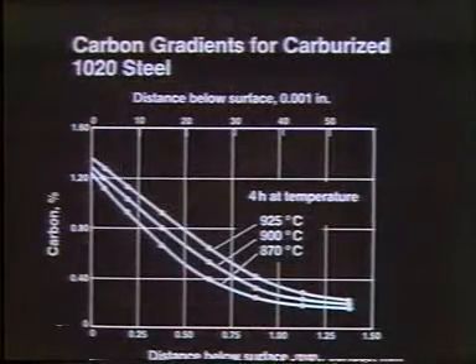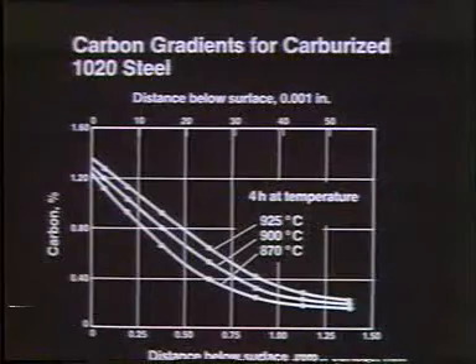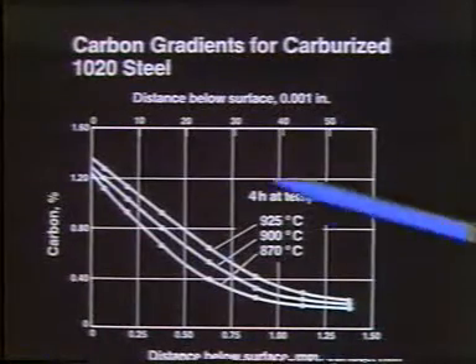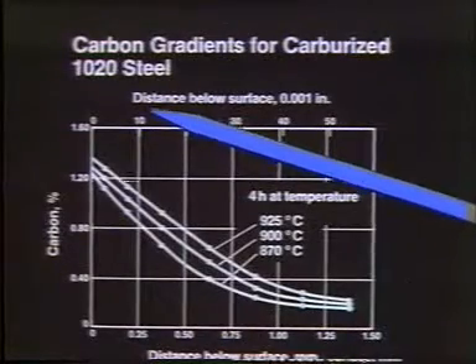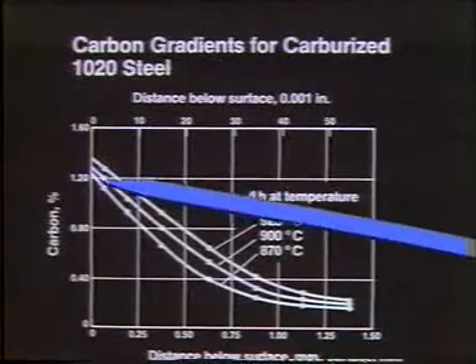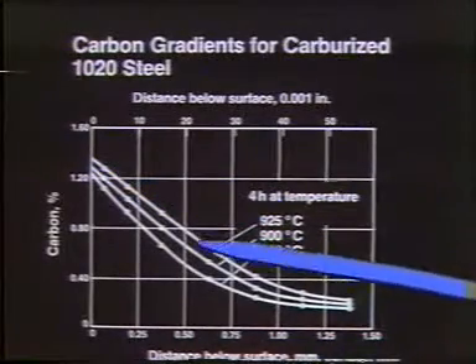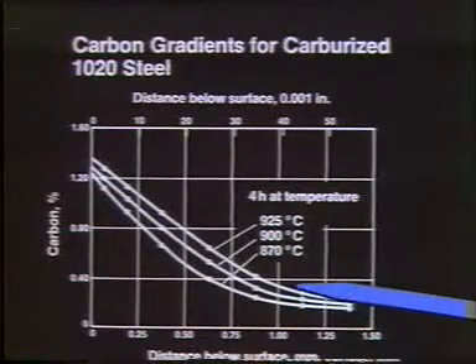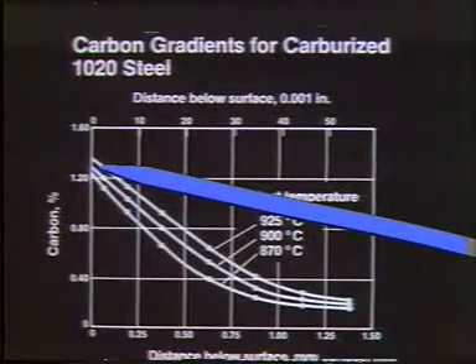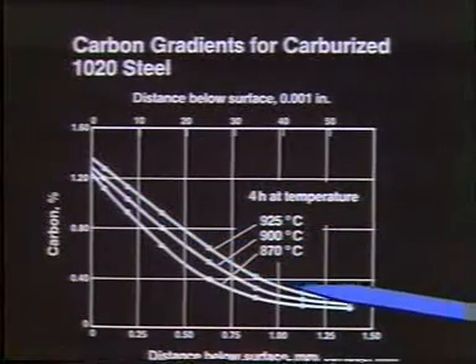Well, after you do this, what you're interested in is what the carbon percentage is going to be, how it's going to be distributed. And again, in this now, we're going to have a temperature variable. And we look at this slide for 1020 steel. This is like taking a very low carbon steel. And we're going to do a carburizing treatment on it. And we want to find out what the carbon content is going to be along that penetration depth. And if we look at the distance below the surface of the material, we find that the carbon content is pretty high. It is hyper-eutectoidal up in this range, and it drops down to a pretty low value at an appreciable depth under the surface.